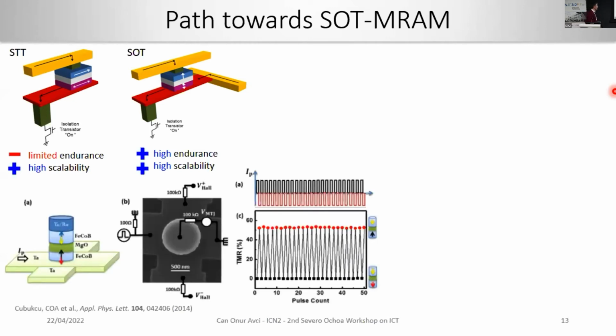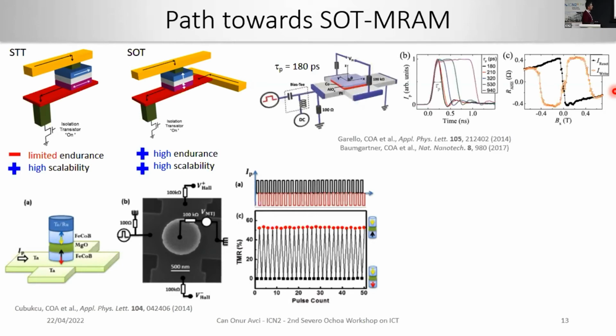We indeed later demonstrated that this kind of spin orbit torque based tunnel junction can work with CMOS compatible materials such as tantalum, cobalt iron boron, and MgO. We have demonstrated a perfect reproducibility of the switching, with a TMR, the tunnel magnetoresistance ratio, of just over 50%. We also investigated other directions, such as how fast we can switch the magnetization. We were able to go down to 180 picosecond switching, which is very fast in devices that are only a few hundred nanometers in lateral size.